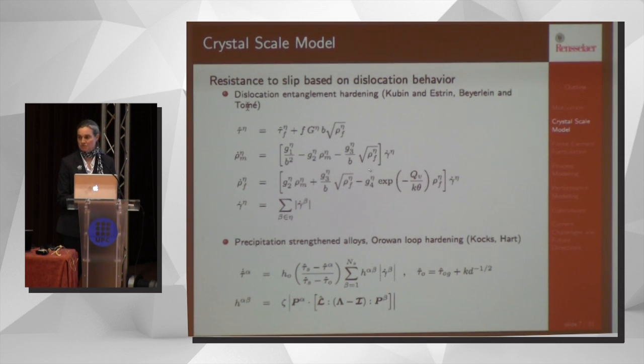So what happens is that the slipping tends to concentrate on the slip system that you start slipping on. So you get localized slip. When you have precipitation strengthening, the self-hardening is actually higher than the latent hardening. So once you start slipping on one slip system, the slip tends to move on to a different slip system, and so you get more different slip systems active and also a more diffuse plasticity.